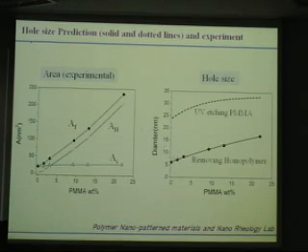But for the homopolymer, the area increases with increasing amount of homopolymer. So the final area is here. This is the prediction. We got the TEM data. So this is very nice. In that case, we can control the hole size from 5 to 15 nanometers.